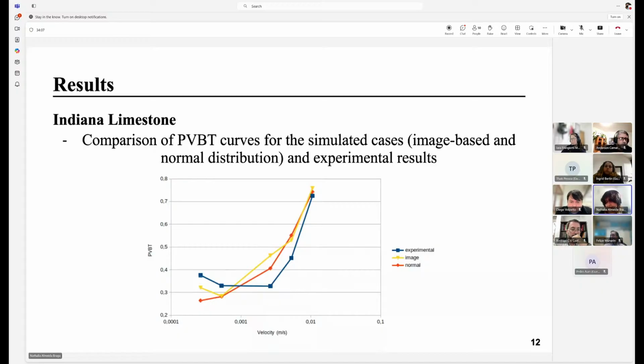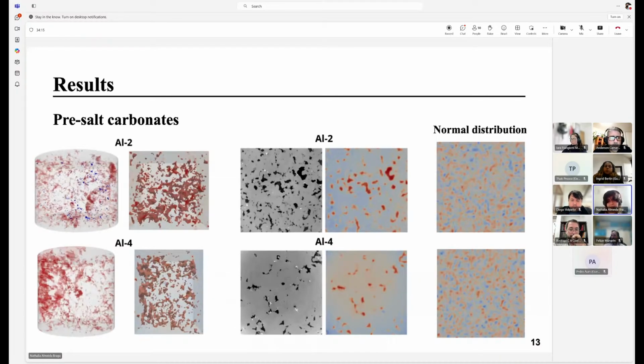But when we have a more heterogeneous system, very different from Indiana limestone, like the pre-salt carbonates, here we have the porosity fields generated from pre-salt carbonates. We have the microscale image of two samples, AL2 and AL4. We see the internal fields generated by the algorithm, and also side-by-side comparisons of the first slice at the inlet face, the micro-CT and the one generated by the algorithm, and the corresponding normal distributions. You see there is a great difference in how the porosity is distributed.